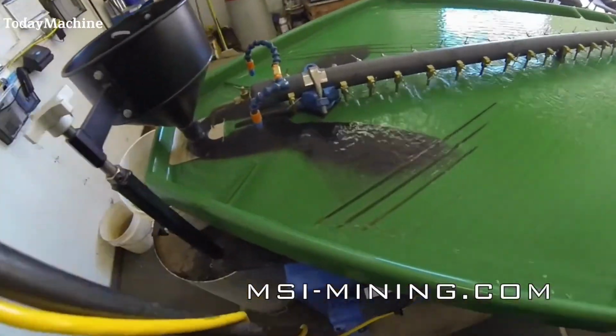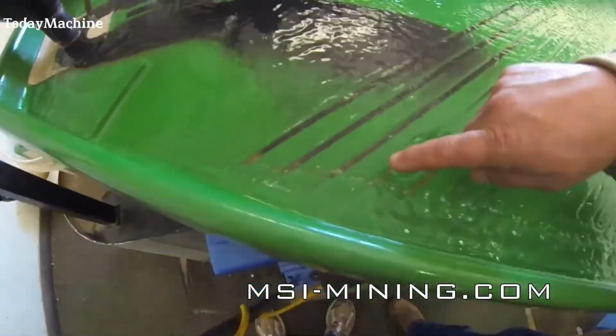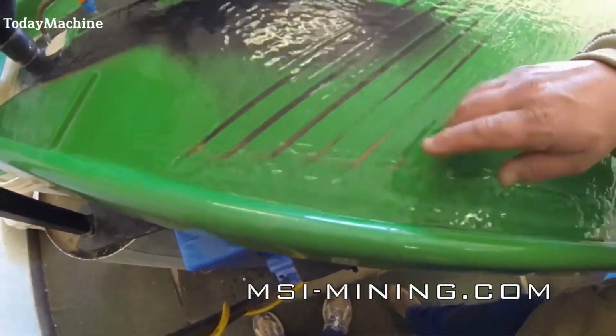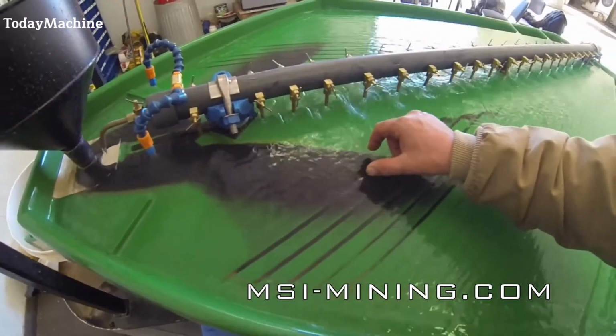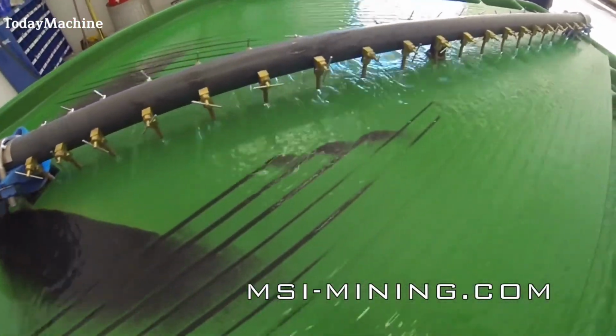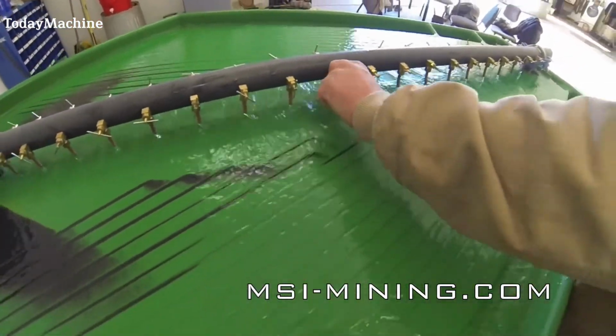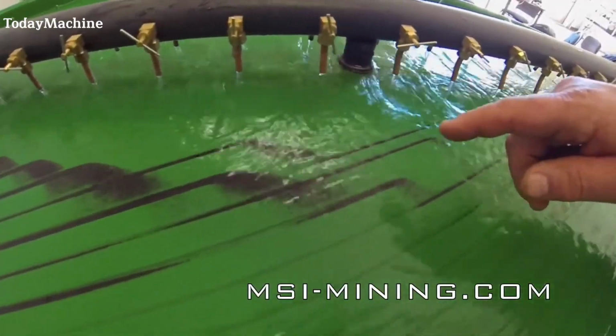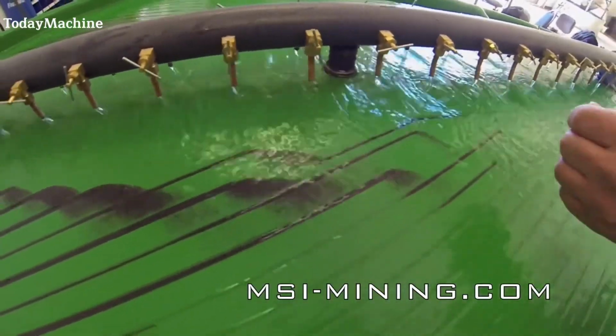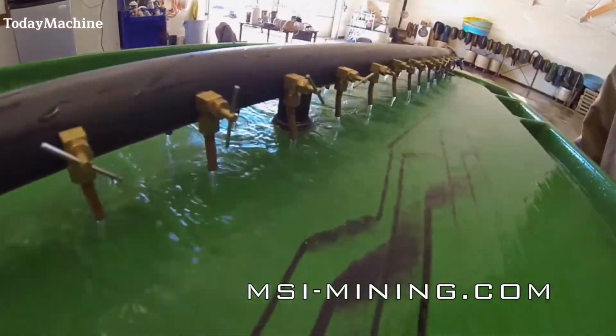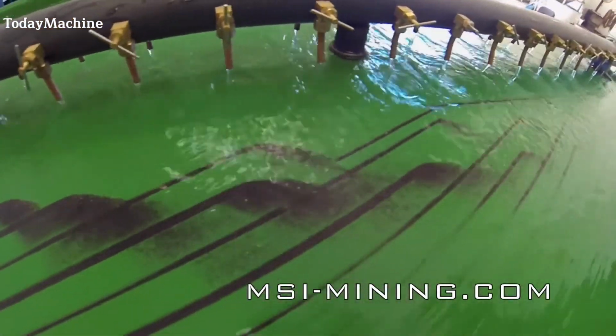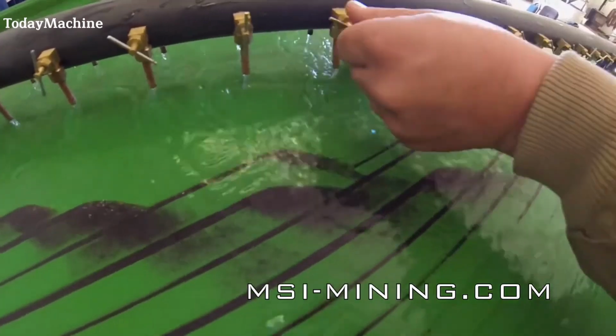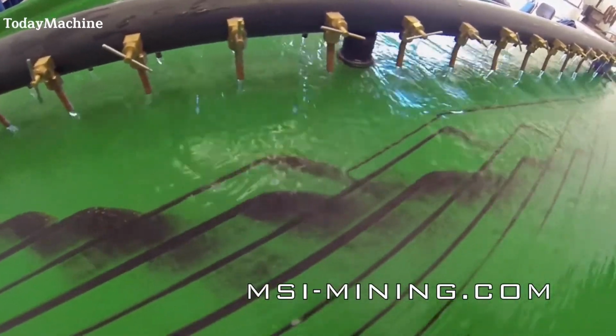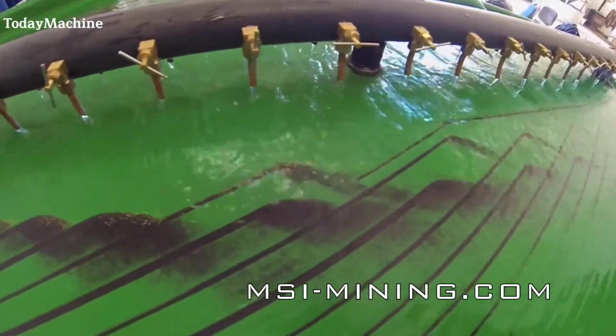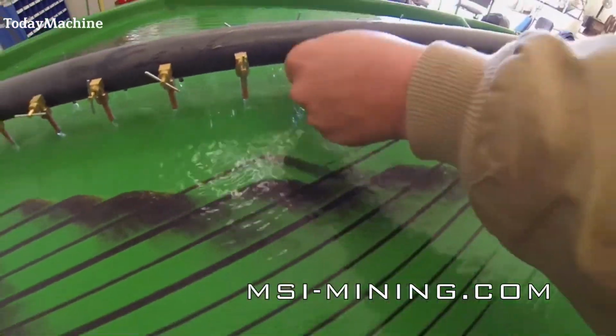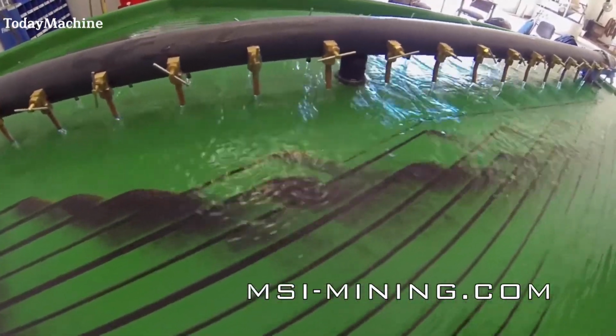Begin by adding a scoop of screened material into the feed system funnel, ensuring there is sufficient water to keep the material wet. Gradually add more material, maintaining a steady flow while monitoring its distribution across the table surface. Monitor how the material separates as it moves down the table. Lighter materials, such as tan or blonde sands, will flow toward the edges, while heavier materials, including black sand and gold, will concentrate closer to the center and the cut lines.